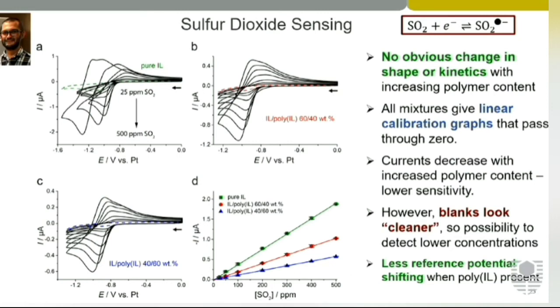So for sulfur dioxide, you can see from the pure to the polyionic liquid mixtures, we also see a similar kind of no change in shape. And it's a bit more clear here. The pure ionic liquid has this impurity peak, which we can see more because we're at low concentrations. And then that impurity peak cleans up quite a lot. So we're able to see these lower concentrations much easier. And I'll also mention, you can see from this one that the peaks are shifting quite a lot. So we have an unstable reference potential, and sulfur dioxide is one of those gases that really shifts the reference electrode. So in the pure ionic liquid, we see quite large shifts, but you can see that these shifts are much less dramatic in the polyionic liquid.